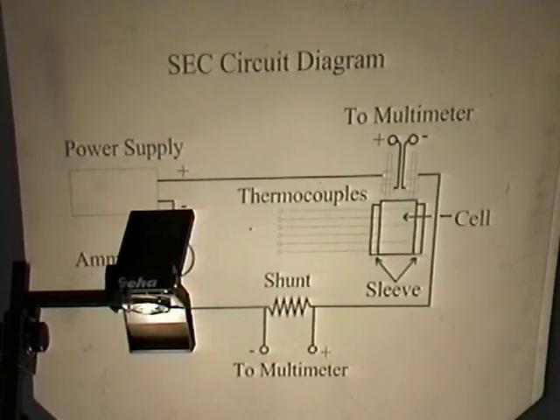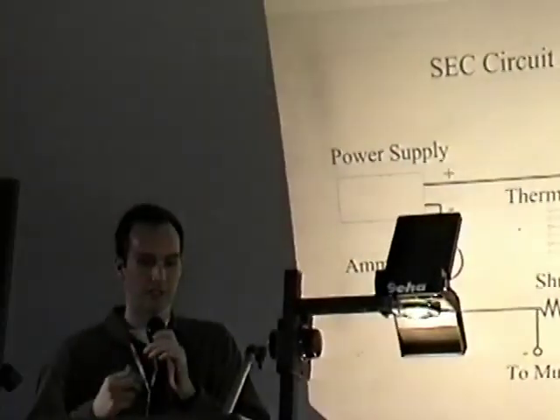Now, inside of the Seebeck envelope calorimeter, we have a cement sleeve that we've built, and it's thermally conductive but electrically non-conductive. And what we've done is we've put 6 thermocouples in the cement sleeve so we can measure the temperature directly at the cell.